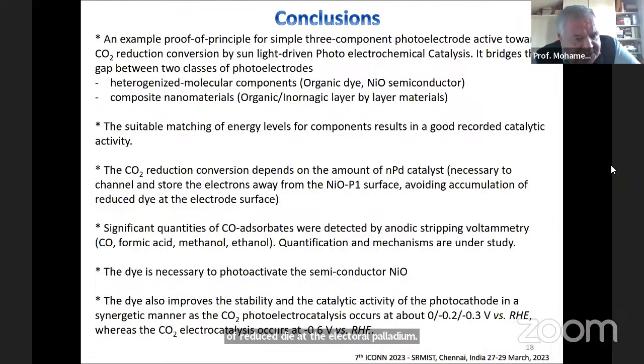We measure significant quantities of CO adsorbates, and we detect them by anodic stripping voltammetry, such as CO, formic acid, methanol, and ethanol, and the quantification and mechanism are under study. The dye is really necessary to photoactivate the semiconductor nickel oxide, and it also improves the stability and the catalytic activity of the photocathode in a super synergetic manner, as the CO2 photoelectrocatalysis occurs in between 0 and -0.3 volt versus RHE, whereas for CO2 electrocatalysis with only palladium, it occurs at -0.6 volt versus RHE.